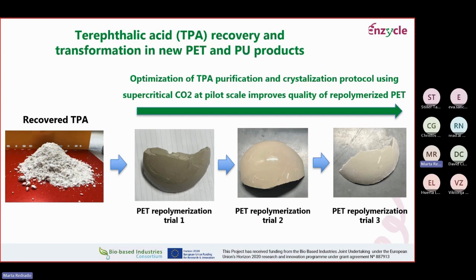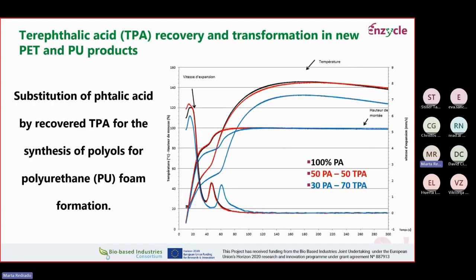And in terms of polyurethane production with TPA, the goal has been to substitute phthalic acid, which is used to produce polyols that in the end are used for the production of polyurethane. So the goal has been to partially substitute this phthalic acid with terephthalic acid. Okay, so we have been testing different substitution rates. As you see in the slide, 50-50 substitution in red and 70% substitution in blue.